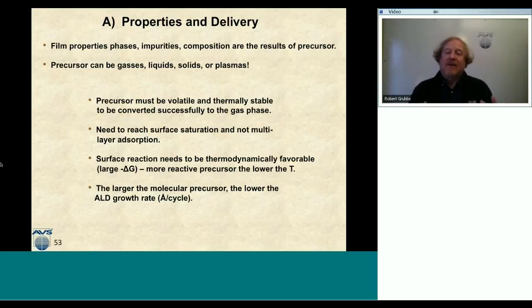And as I mentioned, the more reactive the chemical precursor, the lower the temperature we need in order to run the reaction. So if we want to coat polymers or temperature-sensitive materials, we probably want to use the most energetic, toxic, and pyrophoric ALD chemical so that we can drive that chemistry at the lower temperature to get the ALD to happen on these low-temperature substrates.